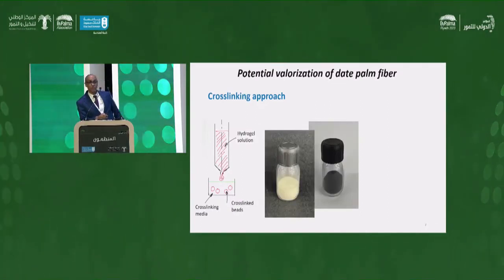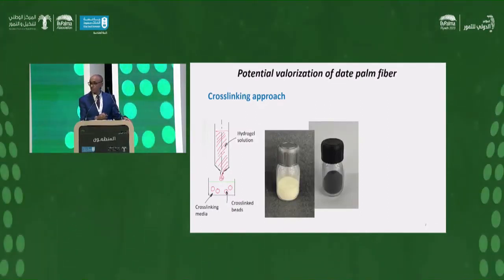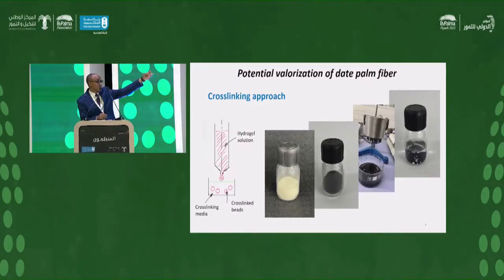This is the same approach used, for example, here for chitosan and the black carbon for specific uses, and we obtain the bead, and this bead can be used for absorption of specific components. For example, we use it for extraction of cadmium from phosphate. As you know, Morocco is the first exporter of phosphate, and in the Moroccan phosphate we have more than 60 ppm of cadmium, and we must extract it.